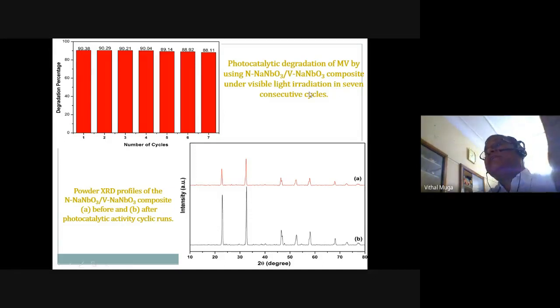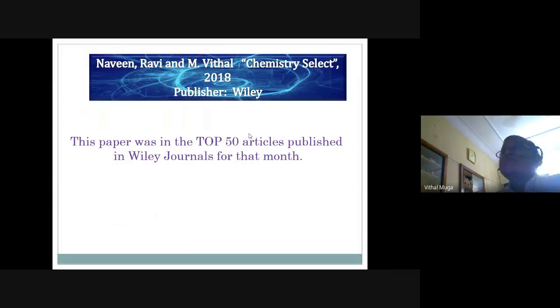Now, another question comes about the chemical stability of the catalyst after 3 hours of irradiation, or 7 into 3, that is 21 hours of irradiation. Now, you see the spectrum here, before and after. Its powder XRD remains the same. That means the catalyst has not changed its structure or transformation. That means this is chemically stable and therefore can be used several times.